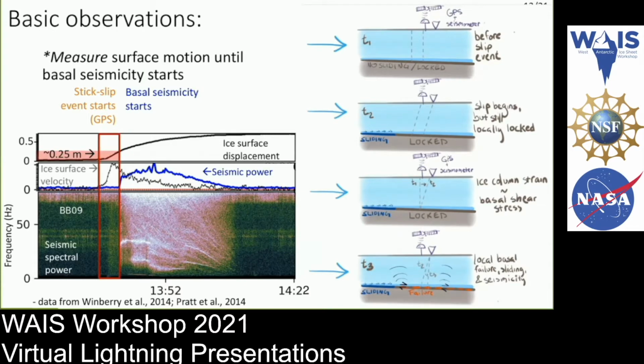So this is neat because we can measure how far the surface moved, assume the ice base did not move, calculate the shear stress in the ice column as a result of the deformation using some assumption about ice rheology, and then estimate the local basal yield stress. So that is pretty neat.